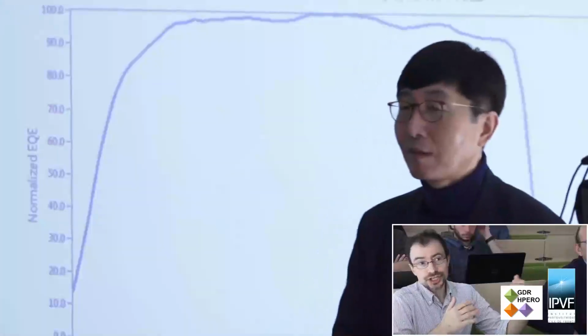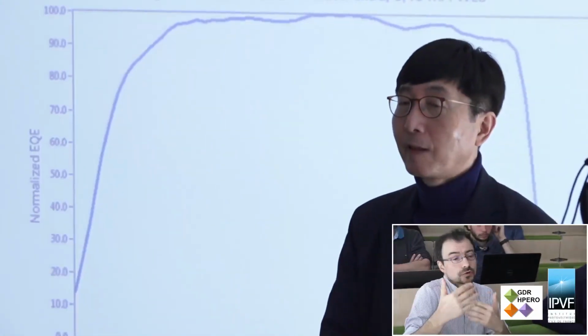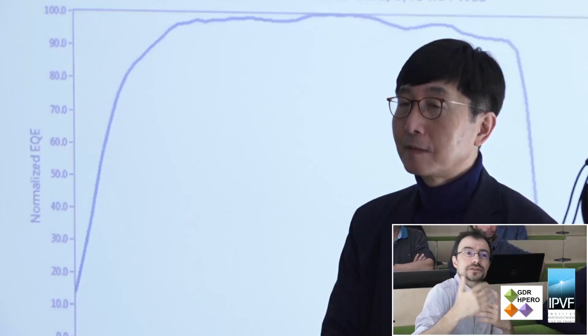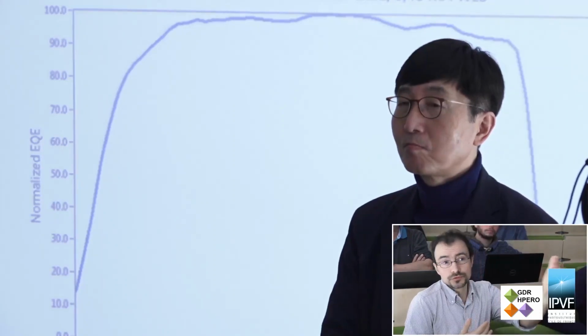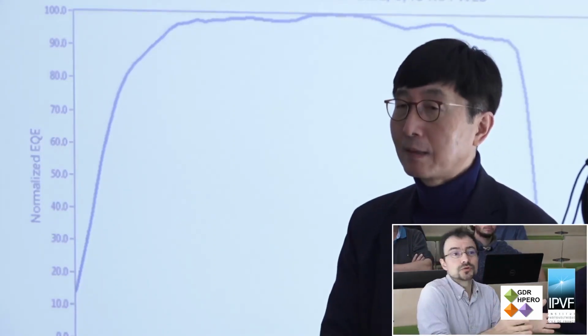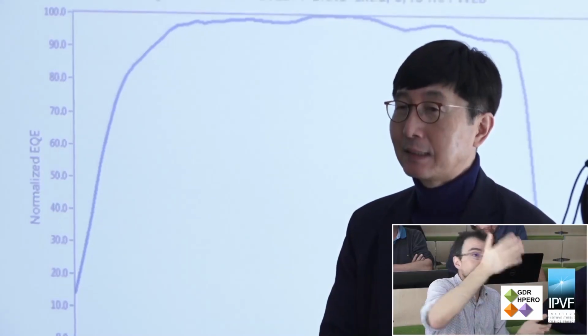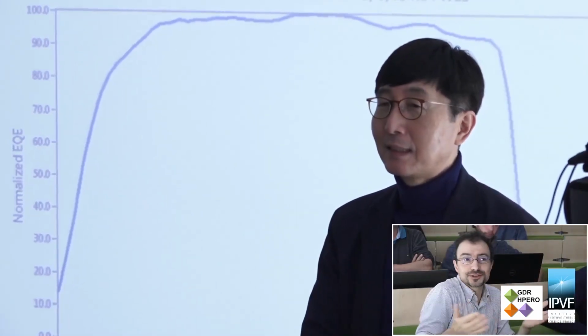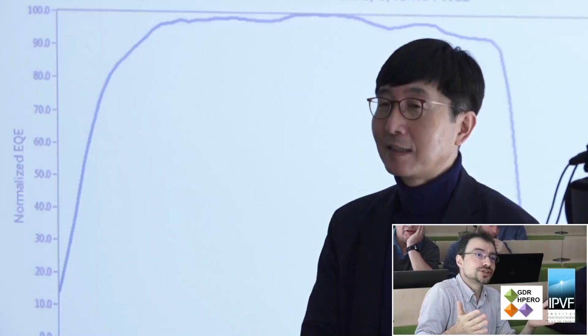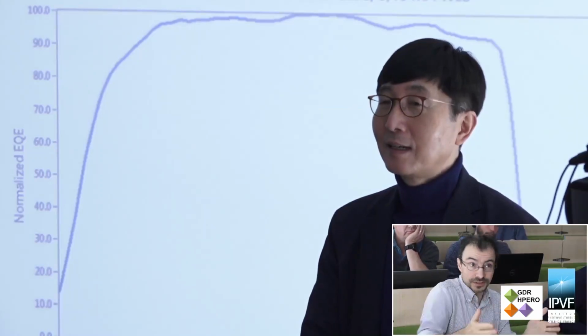So what you pointed out is stability. When you apply a bias, you change the chemical potential of the ions, and this results in a considerable change in the PL intensity, in the quasi-Fermi level splitting, in the lifetime, and so on. That's on the channel. But when you look at the full device, obviously you have a high efficiency, and so it can sustain a much higher voltage across the device.